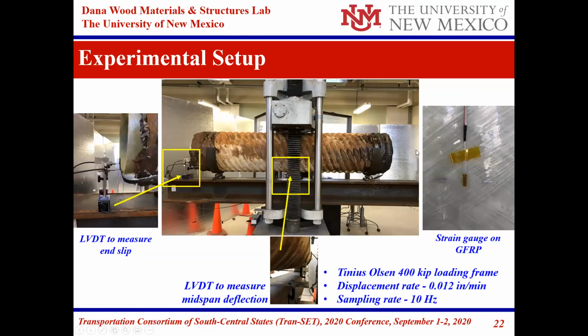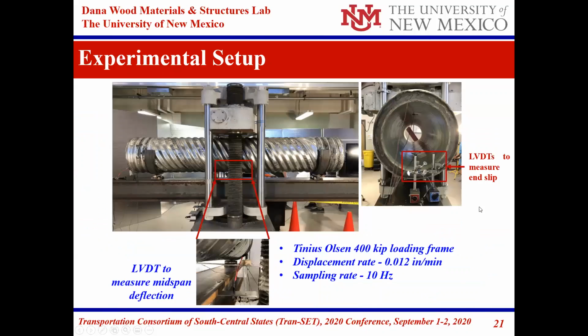The strain gauges are placed inside the GFRP because the whole composite section goes in bending. So if the stress is transferred and the GFRP is now working to take the load, then we should be observing strains in the GFRP. That means the load has transferred completely from the pipe or the corrugated pipe to the glass fiber.